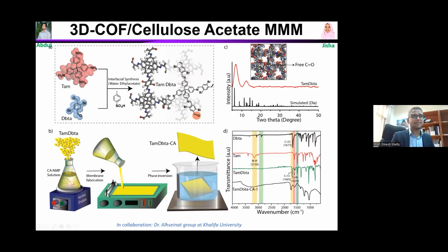That's what we did. We synthesized this again. Of course, we did characterization, but the important part is here. What we did now, we mixed a very small amount of this hydrophobic version of the COF with cellulose acetate. It's a very cheap commercial membrane material. Basically we want to use the 3D COF as pillars, small nano pillars. So we mixed it, then using the well-known phase inversion method, we end up getting this membrane. But we use two conditions. One is we use NMP as a solvent. In the other case, we use DMF as a solvent.